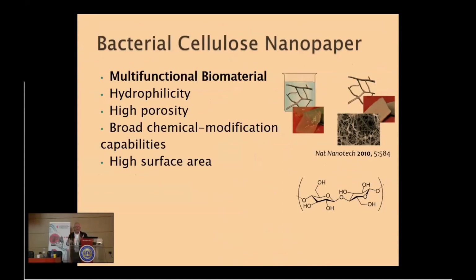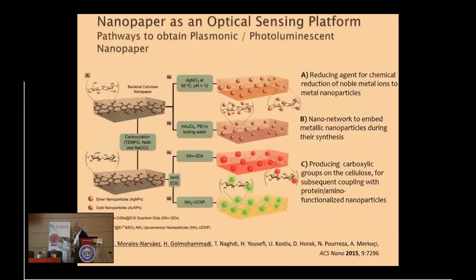But also, we incorporate inside paper nanomaterials, so we are able to transform a piece of paper to plasmonic, fluorescent paper. In fact, for that we use this so-called nanopaper. It's based on nanofibers of cellulose, where we dope with different kinds of particles. We dope with silver, gold, quantum dots, upconverting quantum dots. So either by in situ synthesis of nanoparticles or ex situ preparing nanoparticles and dropping this onto the paper.